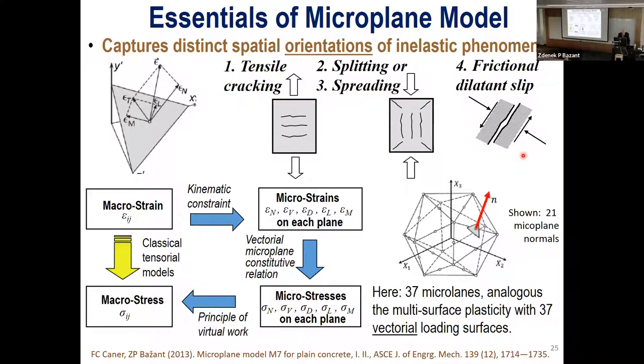There's a model developed at Northwestern in the early 1980s, went through several improvements, the latest one, M1, M2, up to M7, that's what we use. But the basic idea is that there are weak places in the material, and we resolve the strain into a vector on that plane, a projection, which is a component shown here. And if you deal with vectors, for example, for the normal part, you can relate it to distributed tensile cracking. For the compression part, you can relate it to splitting and spreading. For the shear, you can relate it to shear slip. So you can bring in physical ideas, which in tensor setting with loading surfaces, you cannot do.